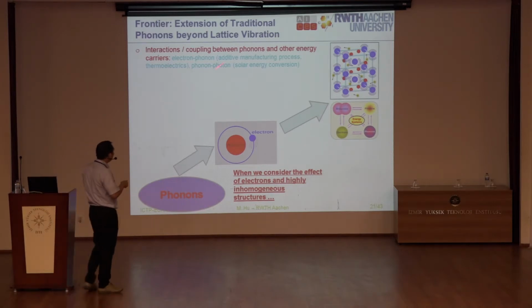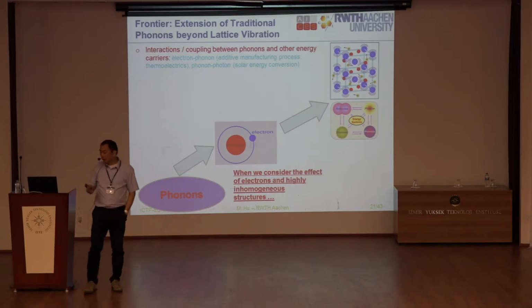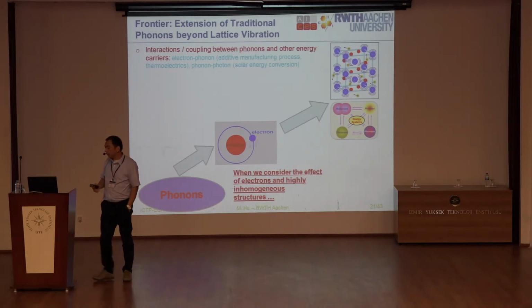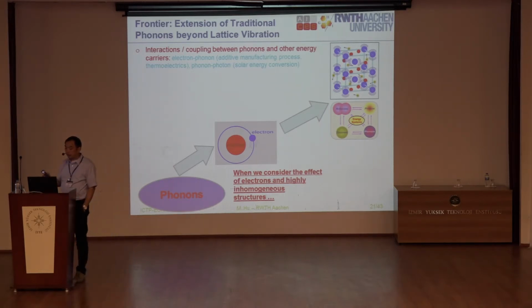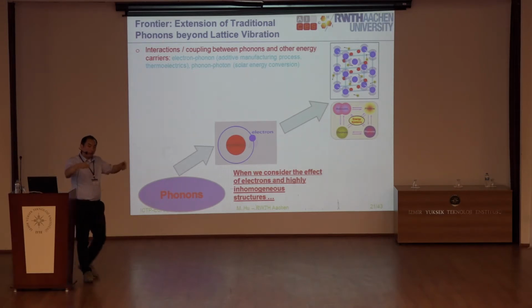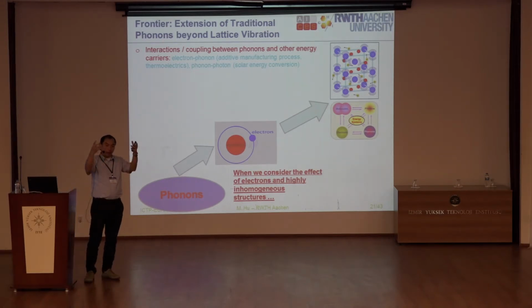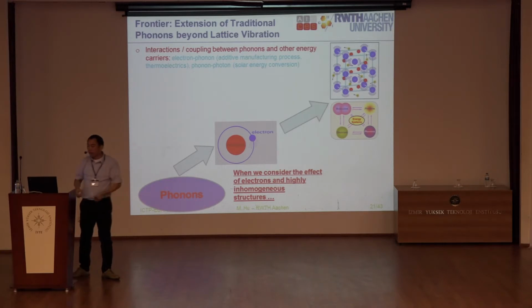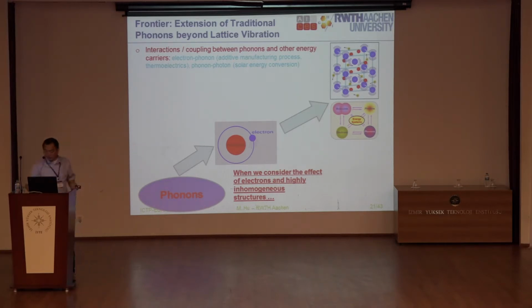And the phonon-photon interaction can be very important for solar energy conversion. Some work has already been done by some groups, and they found that sometimes the phonons can assist the solar energy absorption. Which means that if you have a temperature, the phonon vibration can help the material absorb more energy from the sun.